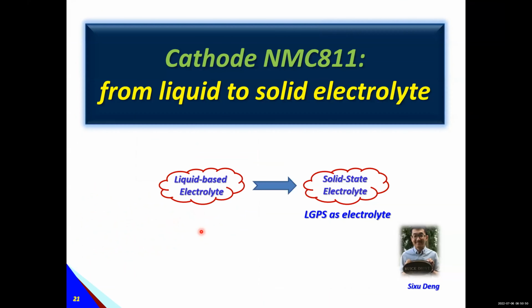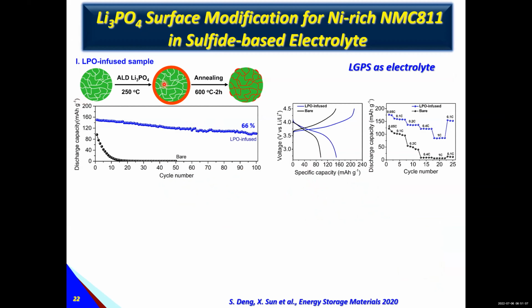So after the liquid system, we try to know if we want to use the sulfide-based solid state system, what difference, even if we're using the similar coating and simple annealing. So we picked LGPS as an example to work on that. So we used the same procedure, coating with the annealing. We found this solid state system is not that good. Without coating it cannot be very good. With coating, still have a challenge.